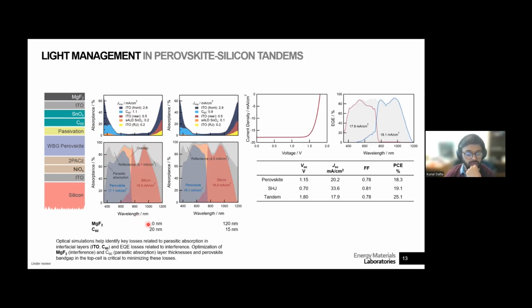So if you then use an anti-reflective coating, magnesium fluoride in this case, so here, and reduce the C60 thickness to reduce the parasitic absorption, you start to get the reflection changes. So you almost halve it. It's at 4.5 now. And that's because the interference is changing quite a bit. So you can see this dip here, and that it goes down significantly. And what you're also changing is the C60 layer thickness, so the absorption there also goes down.